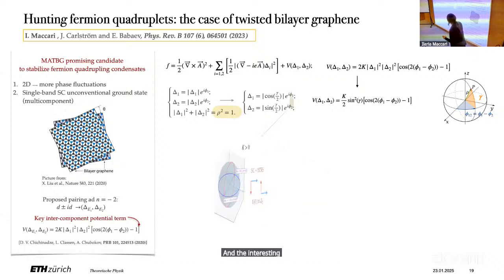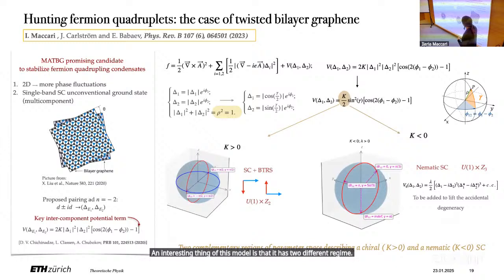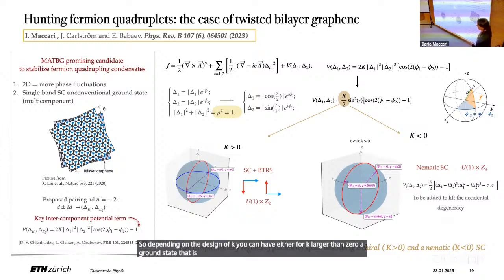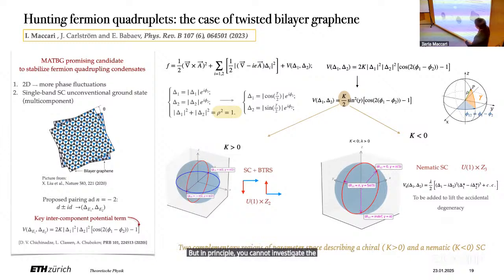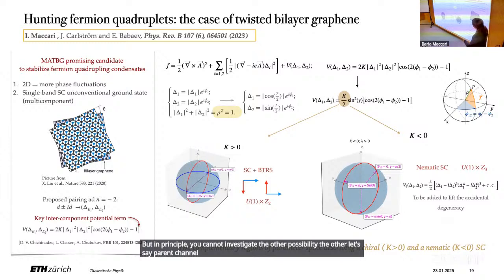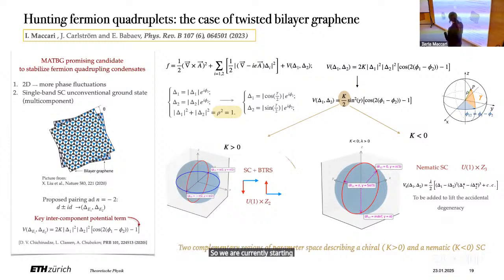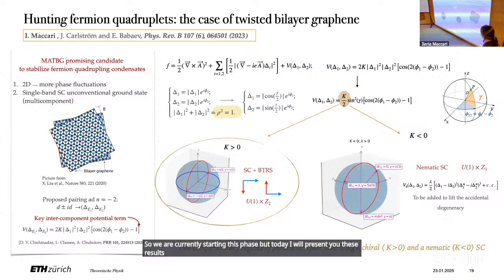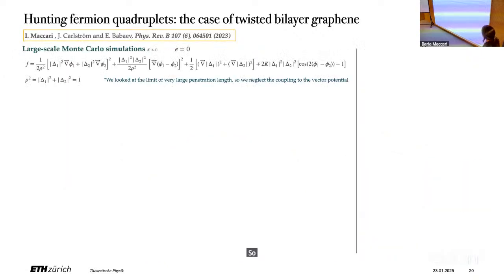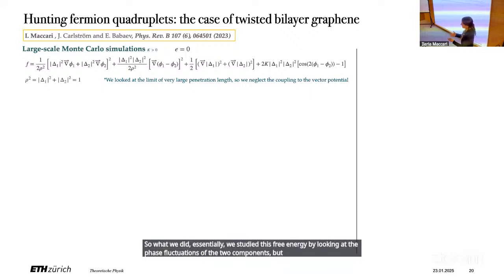And the interesting thing of this model is that it has two different regimes. Depending on the sign of K, for K larger than 0, you have a ground state that is a superconductor breaking time reversal symmetry. And this is the case of this plus minus id. But in principle, you can also investigate the other possibility, the other pairing channel, where K is smaller than 0, and then you have to introduce another term in the functional, where the ground state is a nematic superconducting ground state. We are currently studying this phase, but today I will present these results for this regime. So what we did, essentially, we studied this free energy by looking at the phase fluctuations of the two components, but also at the relative density fluctuations. So we also account for these degrees of freedom via Monte Carlo simulations.